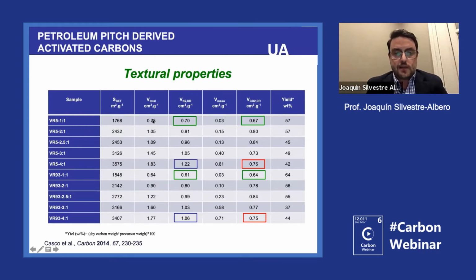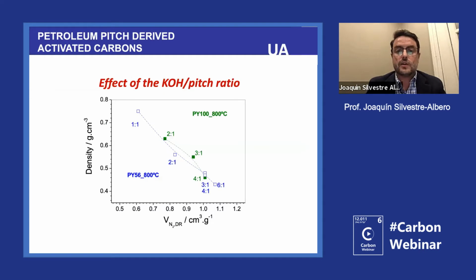Of course, when you see these values, the main idea is, okay, if I want a very good methane storage capacity, I need to activate the material as much as possible. But you have to be aware that when you activate the material, you are decreasing the density. And if we are talking about the design of porous materials for the automotive industry, the density is very important because that will define the volumetric capacity. So at the end, it's not very convenient to go to high activation ratios, because you will decrease the density and you will have a lower volumetric capacity. So you need to reach a balance. You need activation, but you also need to keep the density of the system.